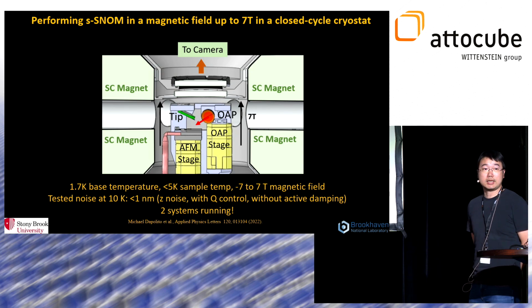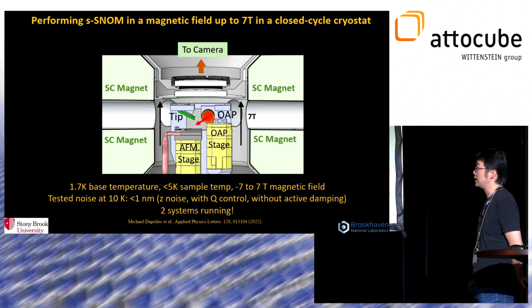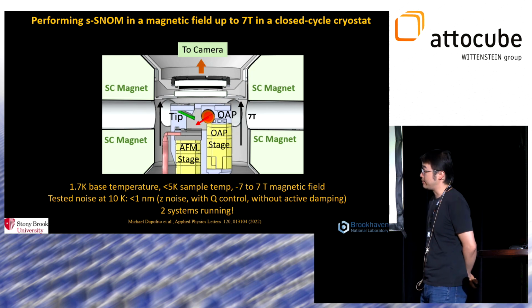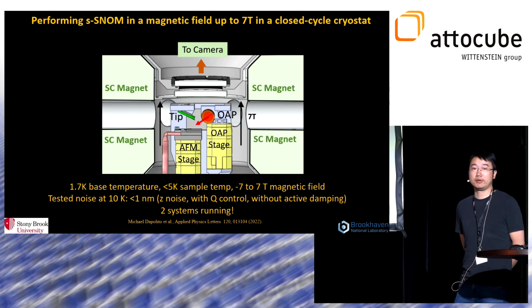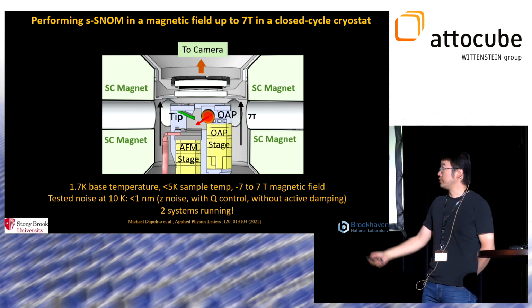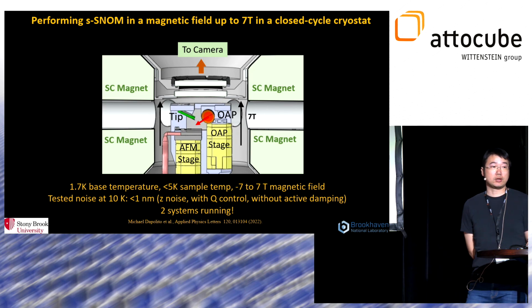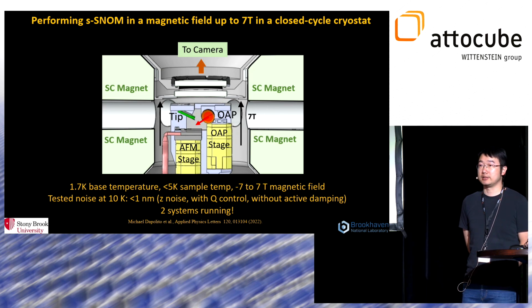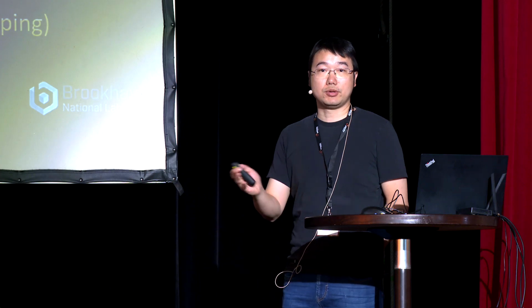The tip noise at 10 Kelvin is below 1 nanometer. Considering this is a closed cycle system, I would say this is not bad. Of course, we are still improving the specs on this. We have 2 systems that are fully running, one at the infrared frequency and the other at the terahertz range. It's interchangeable, but basically you just have to change the windows.